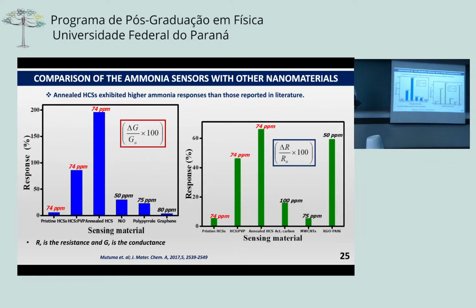If we compare these with other data in literature, most people in literature, unfortunately, don't report sensitivity. I don't know why. They always report percentage response, and therefore we had to recalculate our data to fit literature, which is by looking at conductance, the change in response times 100, and also resistance, the change in response times 100. And our samples exhibited higher response towards ammonia than others recorded in literature. So that means that if we just compare the pristine and the anneals, the heat treatment does change a lot the surface features, allowing for better sensitivity.